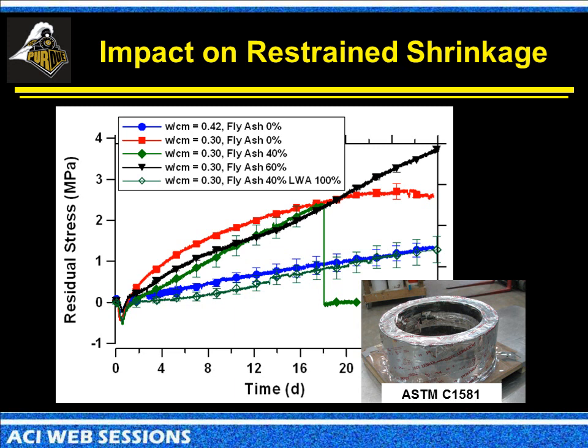Our blue line is the stress development that's going to take place in a standard bridge deck if you don't have any temperature change or any drying shrinkage, just due to the autogenous shrinkage inside of the system. So we may have something like 150 psi after 3 weeks, 4 weeks inside of that system. When we look at the 0.3 water to cement ratio system, we can see that those stresses develop very, very rapidly. And in some cements, if they're fine enough or if we've got finer particles, this on its own is enough to crack the overall system.